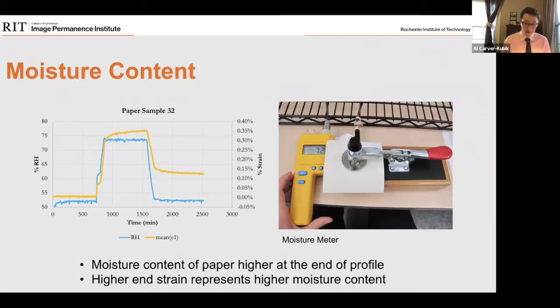Paper samples were placed in our temperature and relative humidity chamber, and we ran profile 5, which was where we began at 50% relative humidity, we increased to 70%, we returned to 50%. Using the moisture meter, which is this apparatus right here, we measured the moisture content of each paper sample. We measured it at the beginning, we measured it at the end of this static RH, or soak period, and we measured it a third time at the very end of the experiment. And each sample had a higher moisture content at the end of the test. Therefore, the higher strain at the end of the test is indicative of a higher moisture content in the paper. So there's just still water in there.